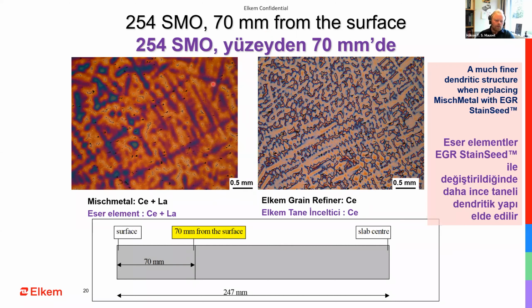Well, before, this steel mill used mish metal for grain refinement of this alloy. And mish metal is of course a mixture of cerium and lanthanum. And this is how the microstructure looked 70 millimeters from the surface. So quite coarse grained. While here you have the results after they used Elkem grain refiner with just cerium. So you can see there is a big difference in the microstructure here. So a much finer dendritic structure when they replaced mish metal with EGR Stainseed.